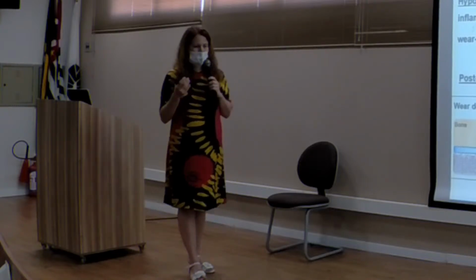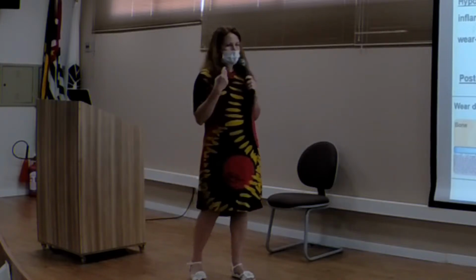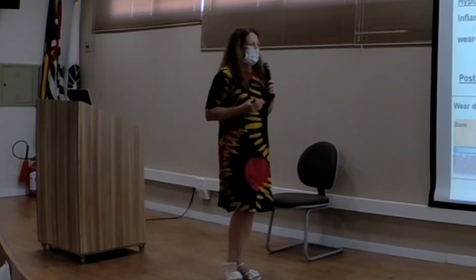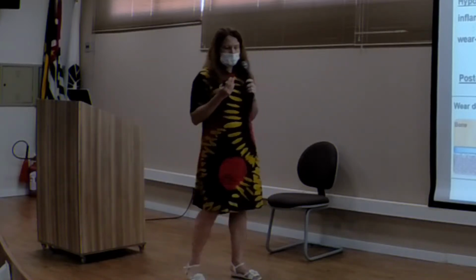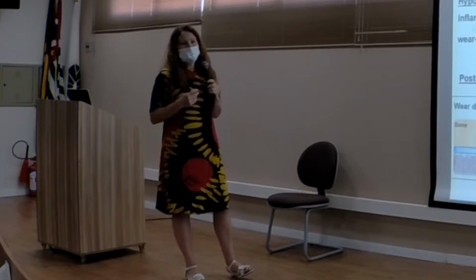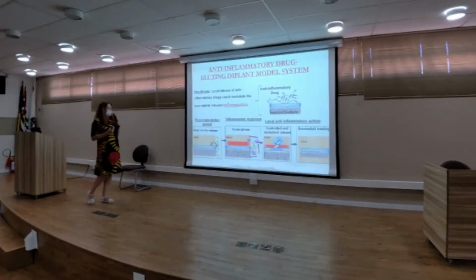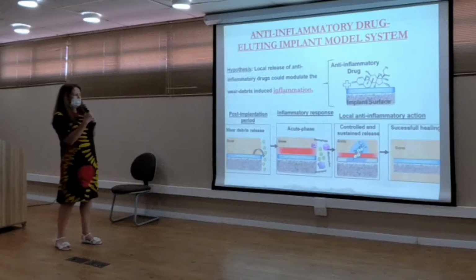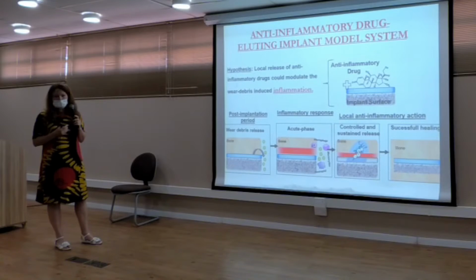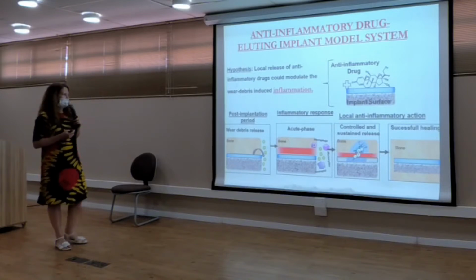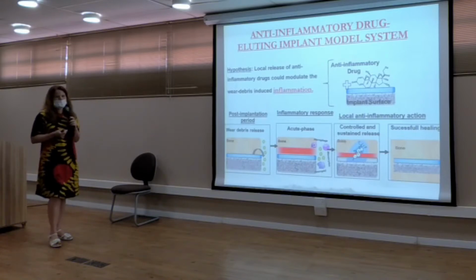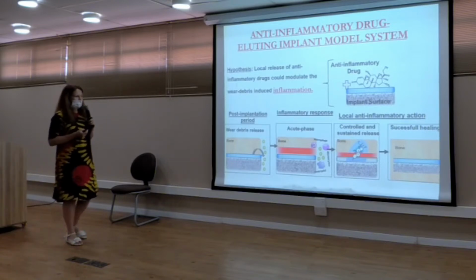So they release nanoparticles to start with, and after this they release microparticles and bigger particles to the surrounding tissue and synovial fluid as well. And this triggers inflammatory reactions. Of course, there are macrophages here, but there are also other types of cells which start not liking these foreign materials, such as osteoblasts and fibroblasts. They start suffering from the toxicity of these implant-released particles, and that's when your inflammation moves to the acute phase. So it's really an inflammatory response which lasts for a long time, and you have to manage that. You have to do something about this. The typical strategy is, of course, taking anti-inflammatory drugs.